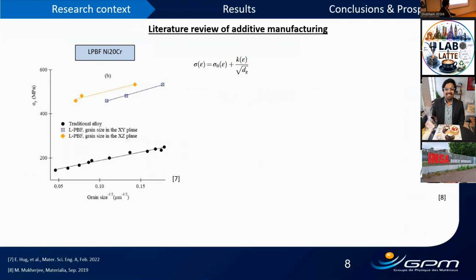Talking about grain morphology, this is a Hall-Petch relationship graph, a graph between yield stress and the inverse of the square root of grain size. What we have here is for nickel 20 chromium alloy fabricated traditionally and for nickel 20 chromium alloy fabricated with LPBF. The slope of these curves explains the grain size dependence on strengthening. And what we see here is that it does not depend on how the nickel 20 chromium alloy is fabricated. We see the same slope. That means we do not have different grain size dependence here.